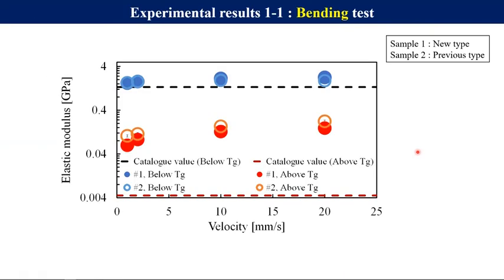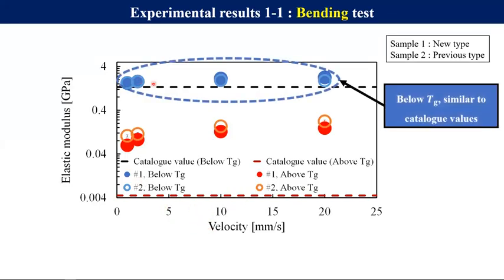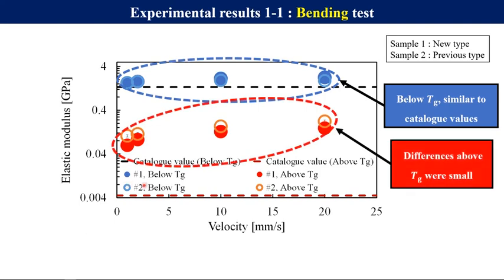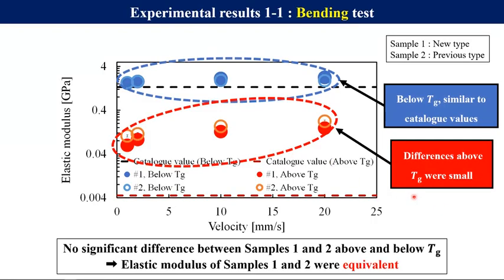So this is the experimental result of the bending test, and the vertical axis of this graph shows elastic modulus, and the horizontal axis shows the velocity. And I'd like to draw your attention to the elastic modulus below TG first. As you can see, they were similar to catalog values. And when it comes to the elastic modulus above TG, they differ from the catalog values, though their respective values were really close. So these results confirm that the elastic modulus of samples 1 and 2 were equivalent.